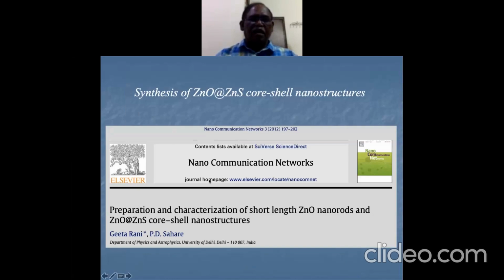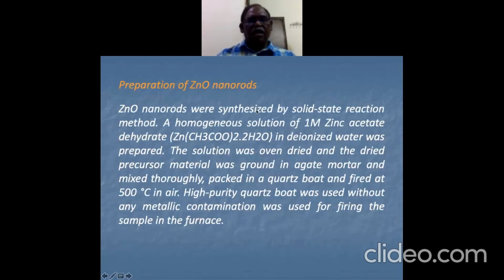Then the same material or the same technique we have used to synthesize this ZnO, ZnS core shell kind of structure. So what we have done is we have firstly synthesized ZnO by the same technique, and over which we then also coated this ZnS. And again, the synthesis is very, very simple, as we have discussed earlier.